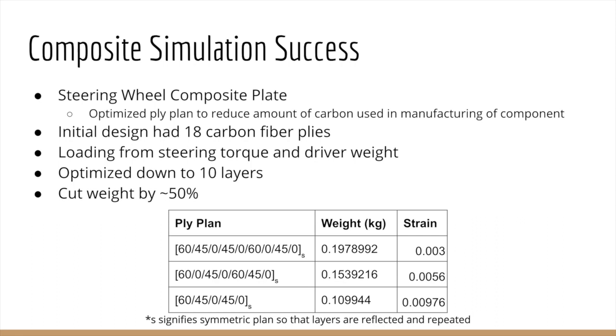The steering wheel analysis was a little bit different in that I was developing the ply plan for the orientations that the steering wheel would be made out of. I was hoping to optimize this plan to reduce the amount of carbon fiber that I needed to manufacture the component, but still make sure that it was strong enough to withstand the loads that we would be putting it under. My initial design had 18 carbon fiber plies, so 18 individual layers. I loaded this with the steering torque and the full driver weight leaning into the wheel. Through optimization, I was able to get down to 10 layers, and this material was still strong enough to withstand the strain.